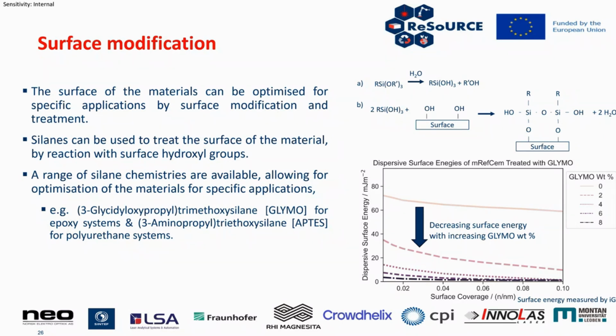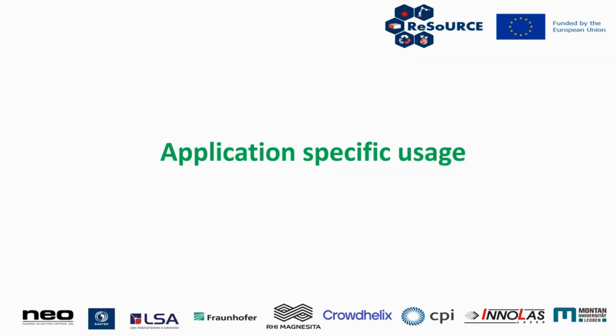And on the right there, you can see the graph where we've looked at different concentrations of the GLYMO on the sample itself. You can see as you load that up, you get diminishing returns of the decrease in the surface energy. So what we can do is, when we're doing applications, we can test to see whether we can put the material in as it is, or if we surface modify it, do we get better applications or better properties from the application. And on that note, I'll now move into some application usages that we've tested at CPI.